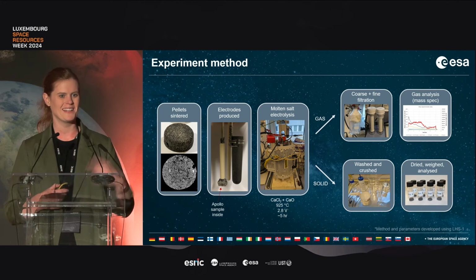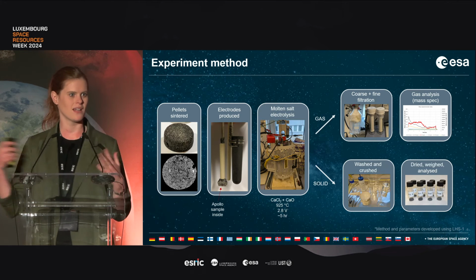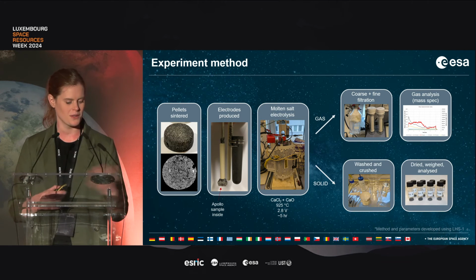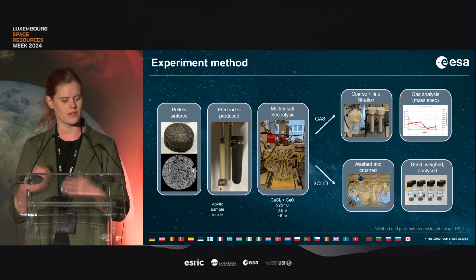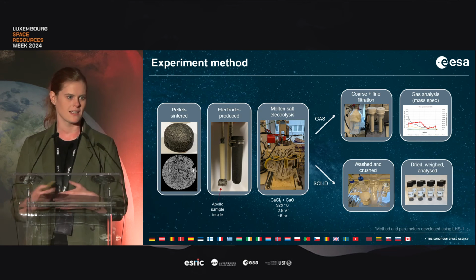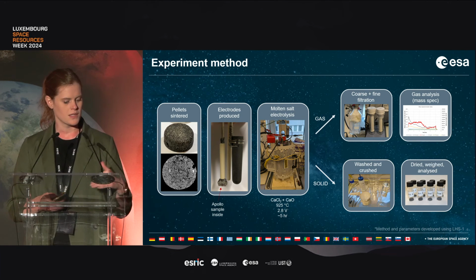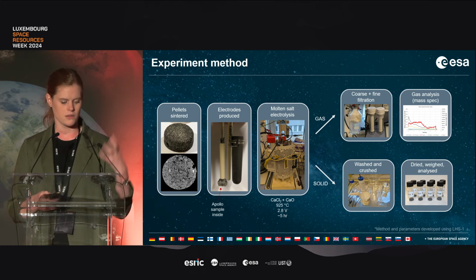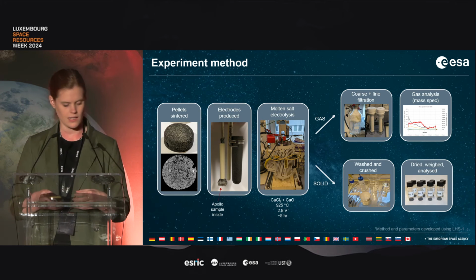duration does not scale linearly, so the time per gram at a larger scale is going to be much, much lower than what we got at this miniature scale. And then for the gas that came out, we went through a coarse and fine filtration, analysed that by mass spec. And for the solid material, we washed the salt off, crushed it up, and then dried, weighed, and analysed it.